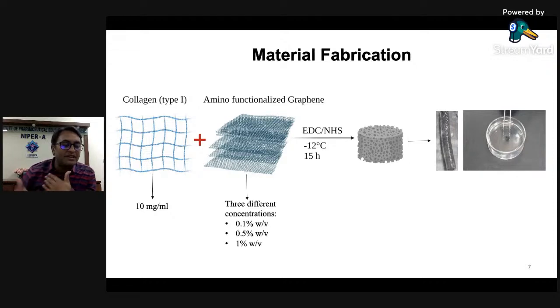But then we again went to the literature and found that graphene materials have also been shown to enhance angiogenesis, and they avoid scar retraction. These graphene and graphene-based materials have also been shown to limit astrocyte reactivity and control macrophage infiltration and inflammation when implanted in a rat hemisection model. So we have another important property of graphene, which we can probably exploit in our material, which is the modulation of inflammation.